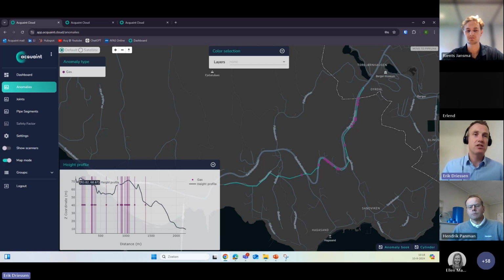So at the bottom, you see the profile of the pipeline again over the 2 and a little bit kilometers. And what you can see is that the instances where we have spotted gas typically are also at the higher points. So what we suspect happened, because all the air vents were replaced or checked prior to the project, is that during introducing the pig, we took some air with us, and we didn't give the system time to de-aerate those gas bubbles at the air vents.